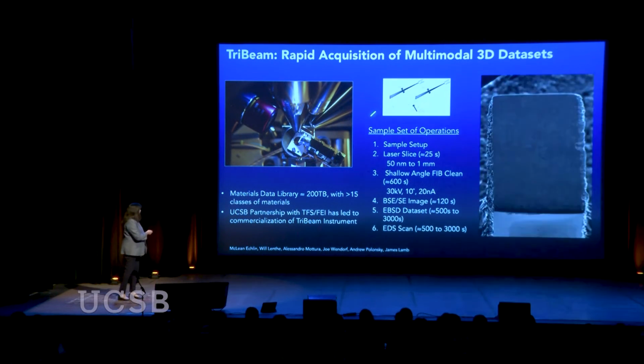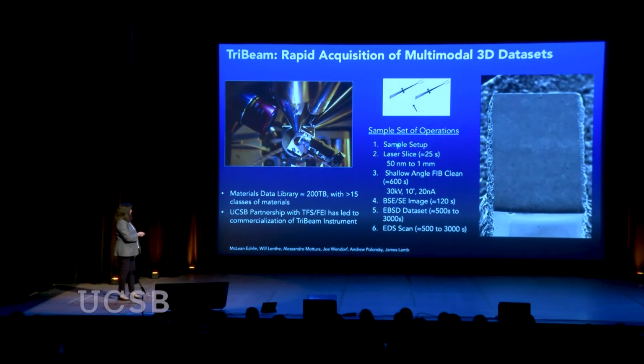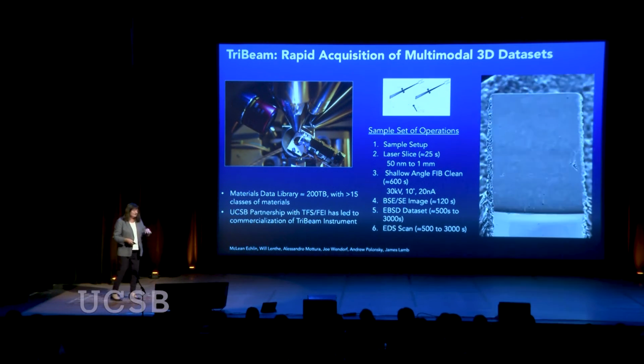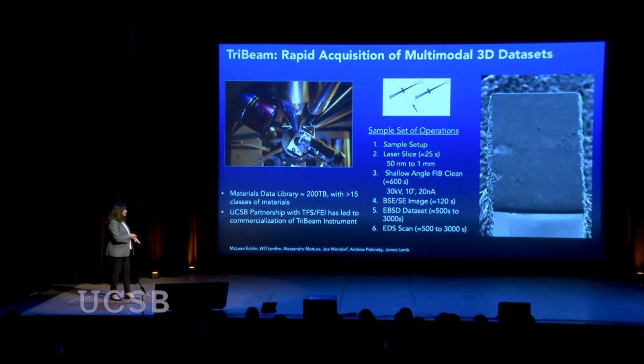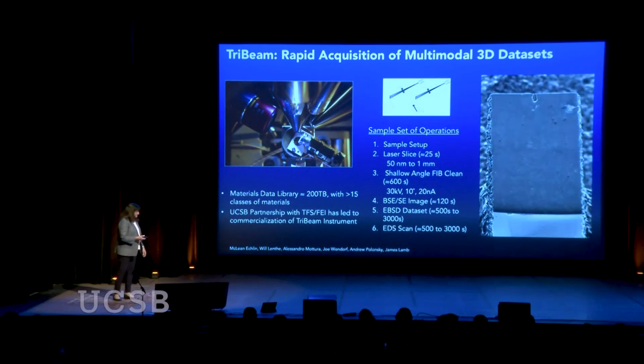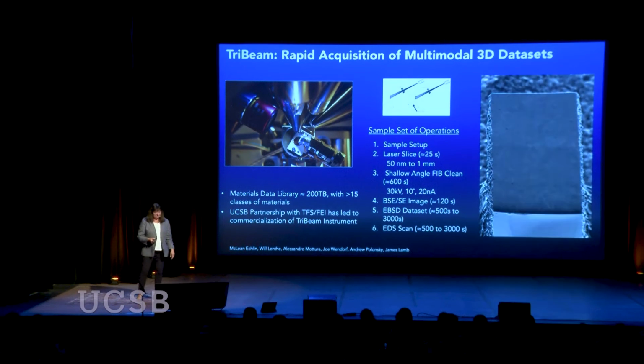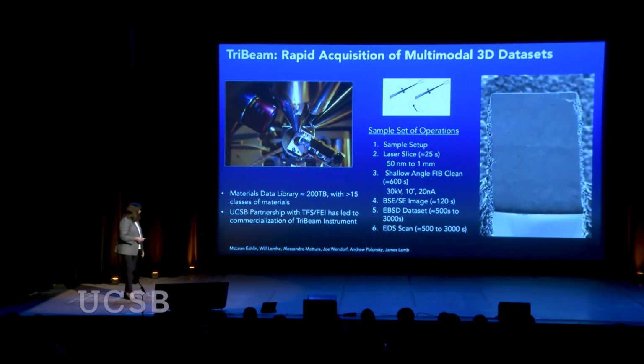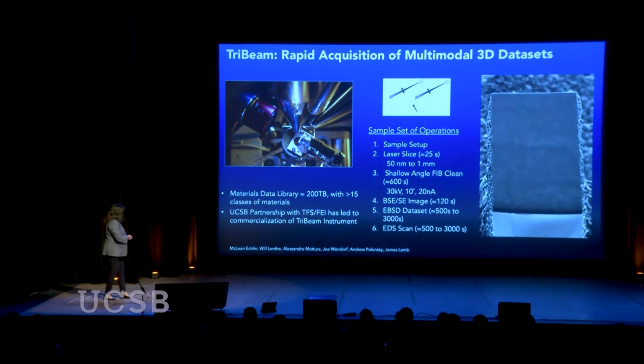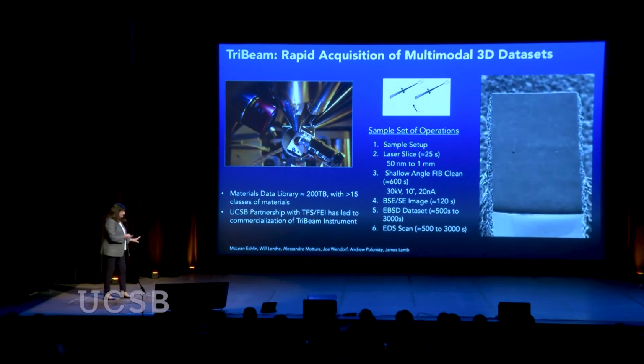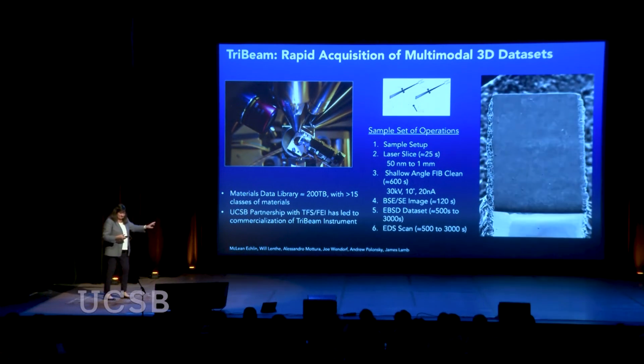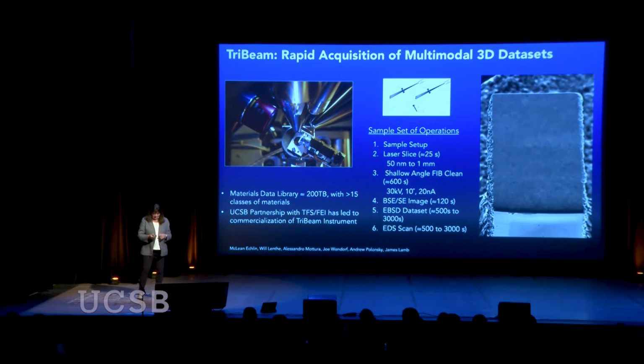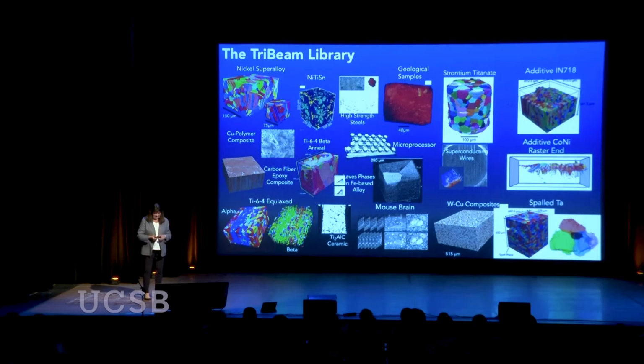And so this gives you some idea how long it takes. People used to do this mechanically, so we can do a slice in 25 seconds. That used to take hours. So this is very, very fast by standards of things that came up to this. And now there's a commercial version, which is much prettier than the one I showed you. It's sitting in boxes in Elings Hall, waiting to be put together.